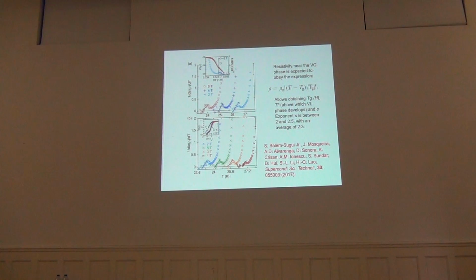Resistivity near the vortex glass phase is expected to obey this expression, and it allows obtaining the dependence of the glass temperature as a function of field, with an exponent between 2 and 2.5, and our experiments show an average of 2.3. And my contribution to this work was in terms of